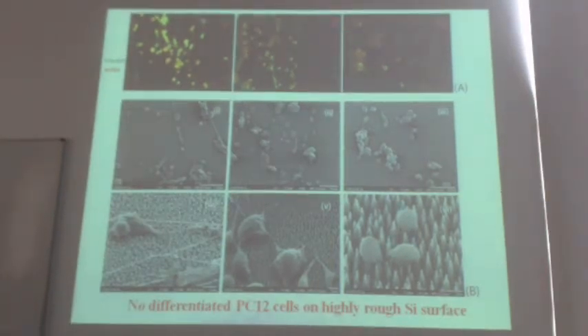In the presence of nerve growth factor, you can see here the differential response of the PC12 cells cultured on these surfaces, as you can see from immunostaining results and scanning electron microscopy images. You can see that in the low and mid roughness, cells can be well differentiated and develop a neural network. However, this is not the case in highly rough surfaces, where there is no differentiation of PC12 cells.